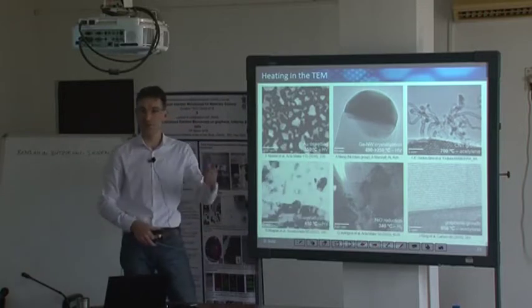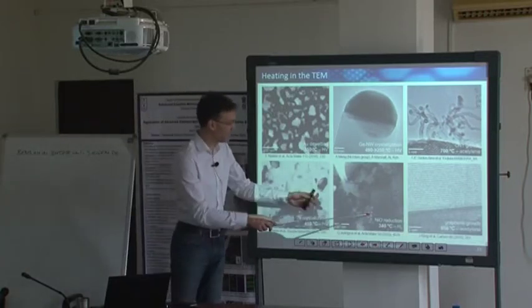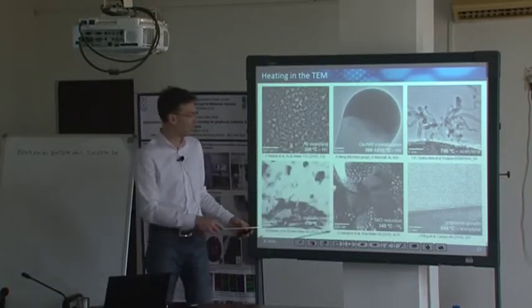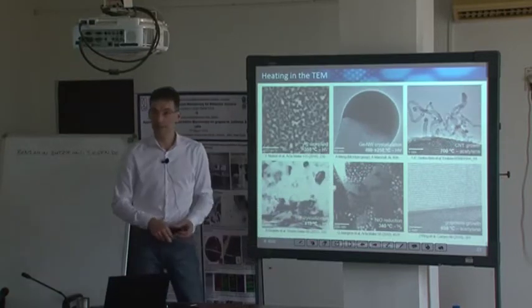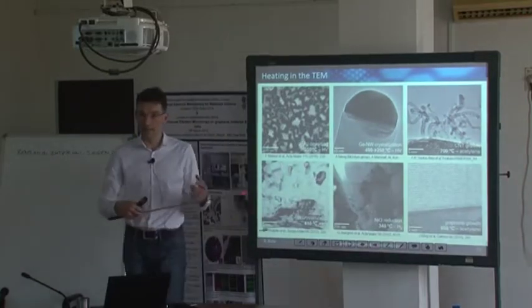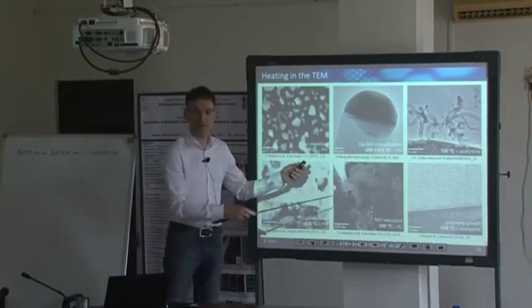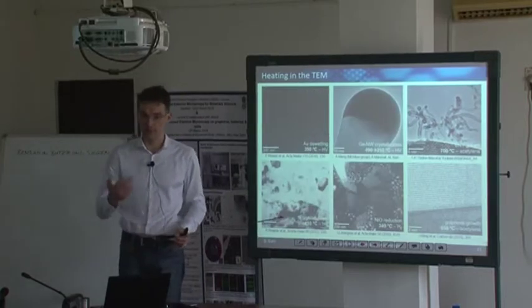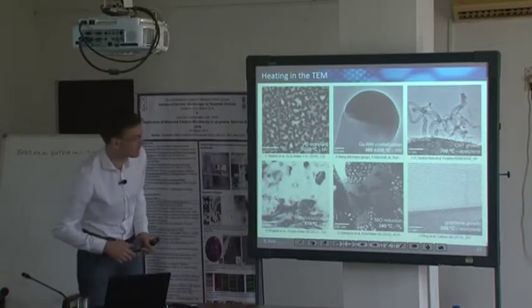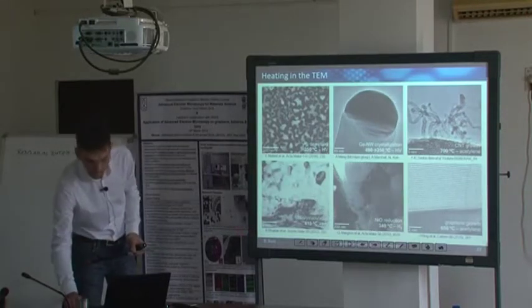Because if you reduce in the first step and then you quench or change the temperature of your fuel cell, you might even end up with a local oxidation and some redox cycling of your catalytically active material. And if that does not densify anymore and you have a composite material, inherent stresses might occur, and that might cause the flaking or the degradation of such a fuel cell anode. So we can see the structural phase transition.